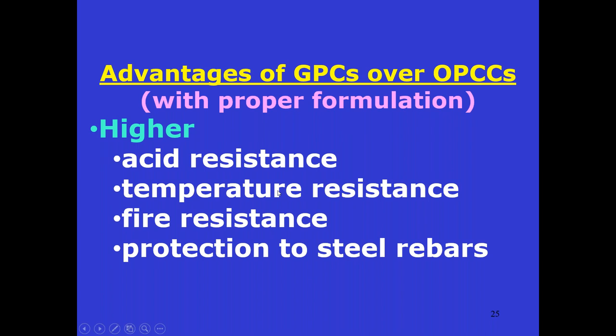We did in SERC with the help of our chemistry PhD scholars and our JRFs of chemistry background, along with civil engineers. So for a dependable science and technology project, we developed a temperature resistant mix, which gets strength after 800 degree temperature also. It will not lose. That strategy I made. Similarly, fire resistance, because temperature resistance comes, fire resistance will come. And the protection to steel. So the pH should be high, and the pH is sufficiently high for protection to the rebar here. There is no problem here.